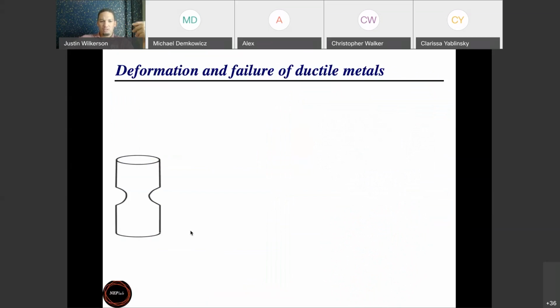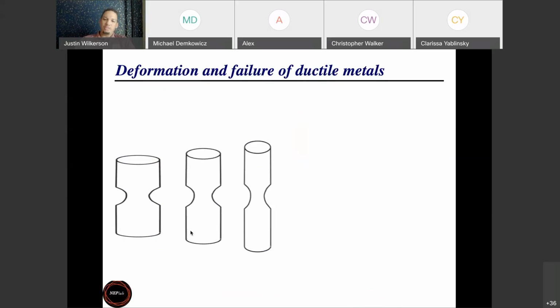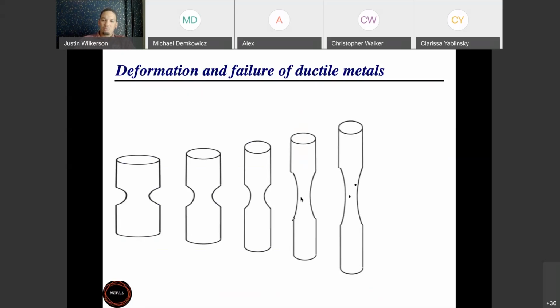So here I have a little cartoon of a notched bar, and we're going to just pull that bar vertically. And what you see is first you get some Poisson's contraction as you elongate the bar. You elongate it further and you get even more. Maybe you get a little bit of necking. The necking starts to become more severe as you continue to pull, so you get more thinning in the middle of the specimen. And then finally, after I've applied a good amount of deformation under quasi-static uniaxial tension, let me say it's specialized to that scenario.